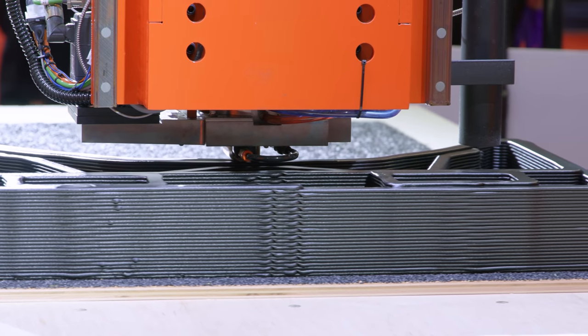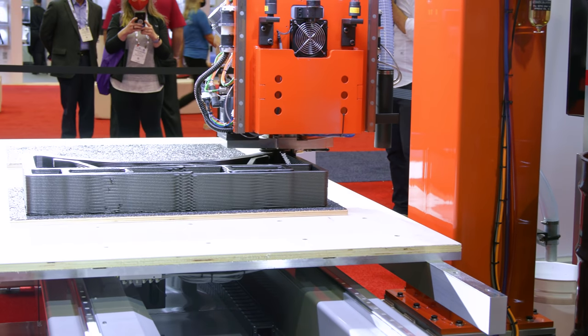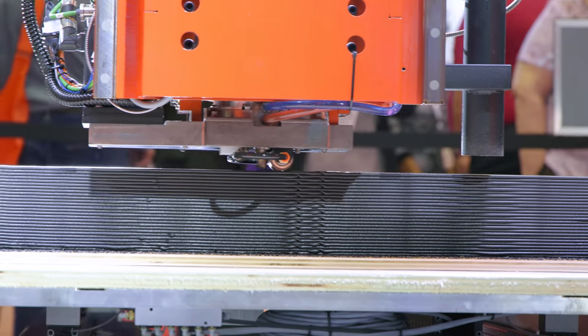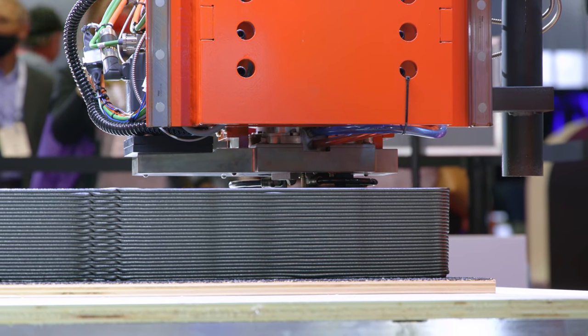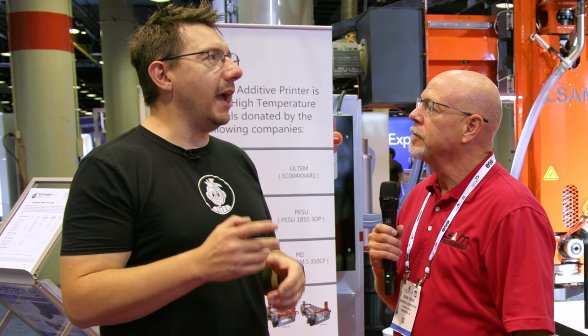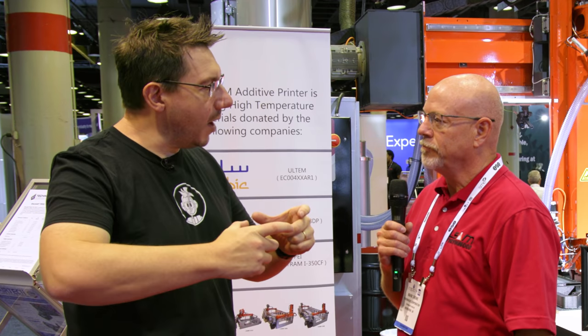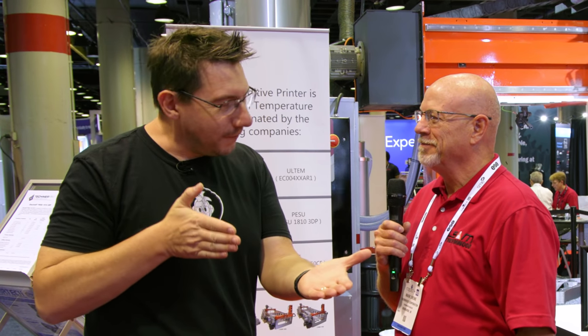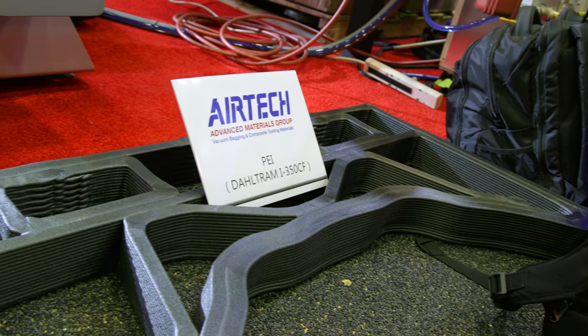We actually have a roller wheel that follows the extruded bead. So for maximum adhesion between layers, we extrude the bead through a 1/2-inch nozzle, and the roller wheel basically rolls over the top of that. And the roller wheel follows the nozzle, follows the design. Oh, okay. So I was thinking, when you see a concrete printer, it has almost like a square or a rectangle nozzle, for directionality, right? Right. But here you still have a circular orifice, and that roller wheel follows the path of the extrusion to squish it down a little bit. That's correct. So you get great Z adhesion. Great Z adhesion. That's what we want.